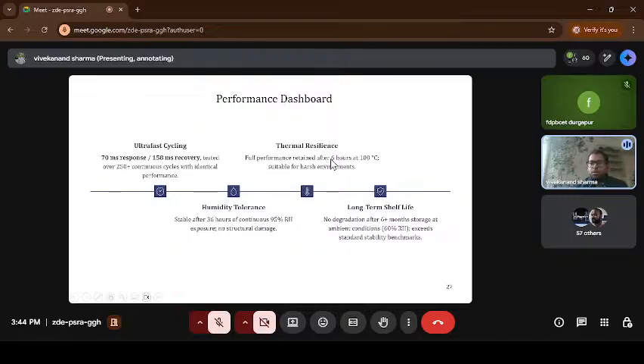It was also stable. We have tested this stability for 6 hours at 100 degrees Celsius. It means that this was stable at high temperature also. Humidity tolerance, we have studied: we continuously kept the sensor for 36 hours in very high humidity, 95%, and the sensor doesn't degrade its performance. Also, we have tested the same sensor after 6 months, and we have found that the sensor was behaving as before. It means that the shelf life of this sensor was definitely more than 6 months.